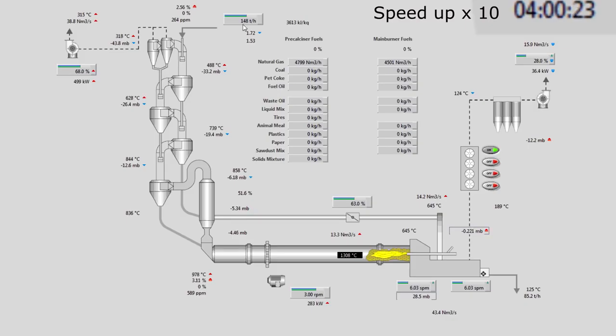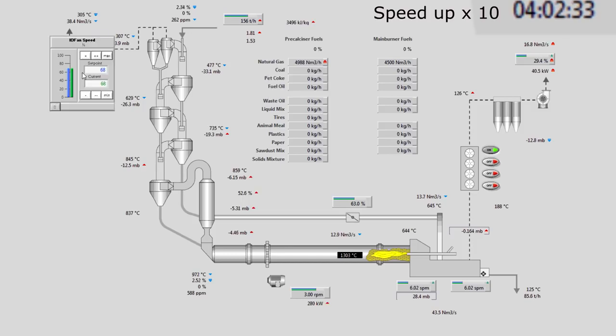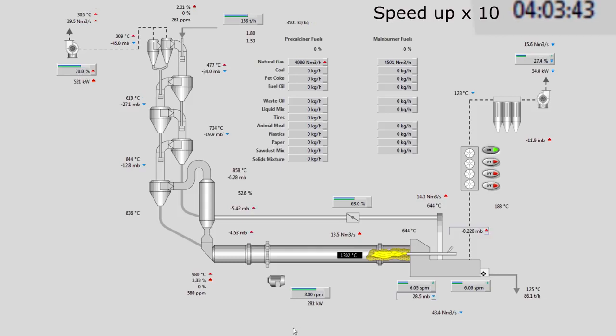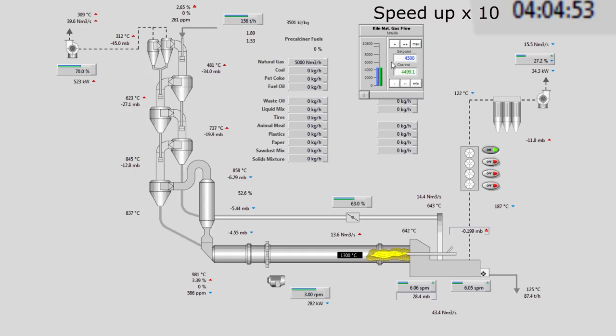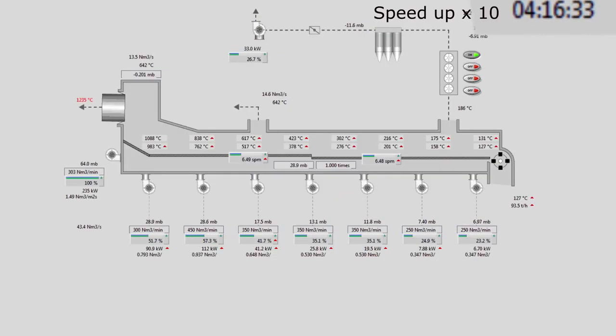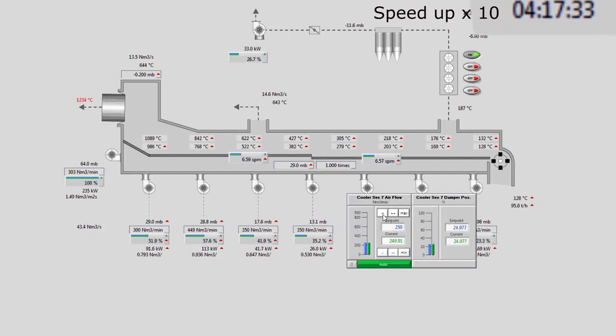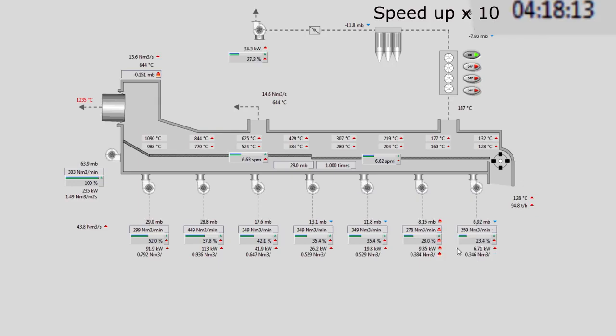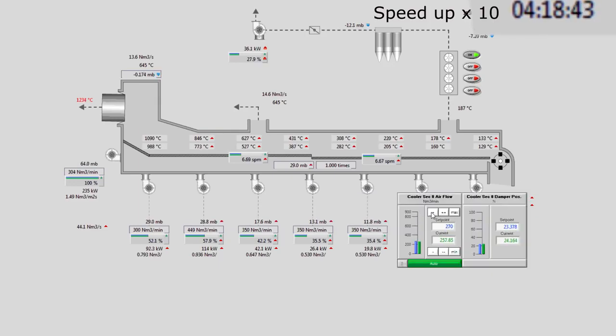Four hours, going to 156 tons per hour. Kiln is running at 3 RPM. Precalciner fuel is still at 51.6%. The cooler is stable, though I see that the clinker temperature is increasing, and I still have the fan number 1 not able to deliver its flow, even at 100% damper. Too much material in that zone, I need to increase the grate speed.